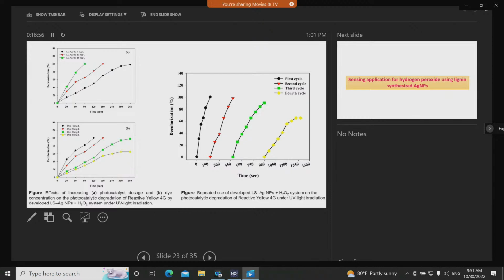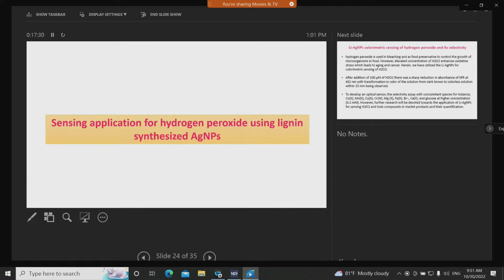And regarding the repeated use of this developed photocatalytic system, we know that catalyst reusability, stability, and lifespan are important factors to develop in the photocatalytic process for long-term application. So here, our lignin-mediated nanoparticle showed a significant photocatalytic activity up to the third cycle consecutively, with complete dye degradation achieved, which can indicate the commercial applicability of this synthesized silver nanoparticles.